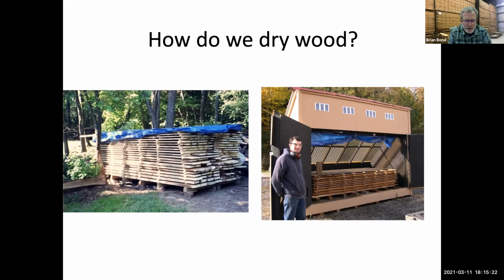You can stick it out on the air dry yard and you can dry it down probably here in Virginia to about 12 to 14%. I'm going to be a little high on that 12, probably go about 13, 14%. But if I leave it out there long enough, it will eventually get to around 12% moisture content or a little higher. Problem for me in Virginia is the relative humidity is usually too high for the moisture content of the lumber to get any lower. And so if I want to use that wood in an interior environment, I want that wood to be around 6 to 8% moisture content. I'm never going to get it there air drying here in Virginia.